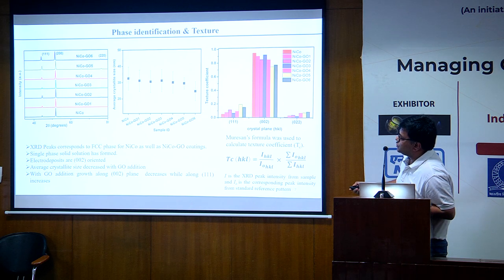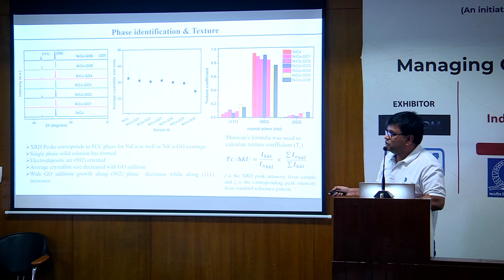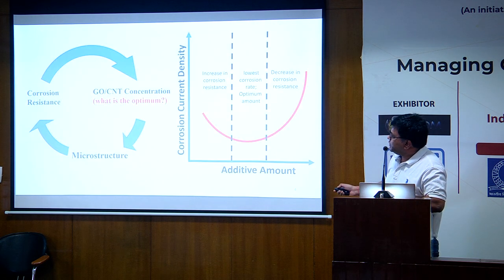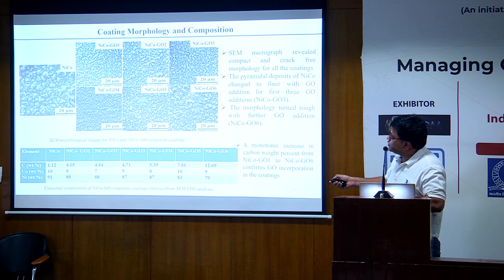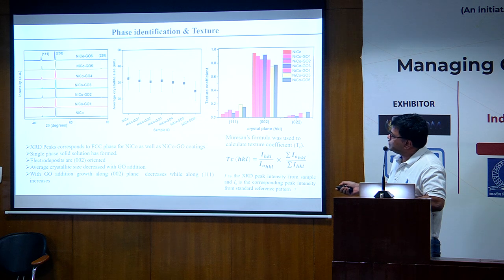And GO1, GO2, GO3, GO4 is the addition of different volume fractions of the graphene oxide into this coating. So if you look back here, we are basically moving in the x-axis. And what we have produced is the coatings with different amount of GO. And what we are going to study is the y-axis. And these are these coatings. So this is increasing graphene oxide addition, and there is not much change in the morphology or the phase.